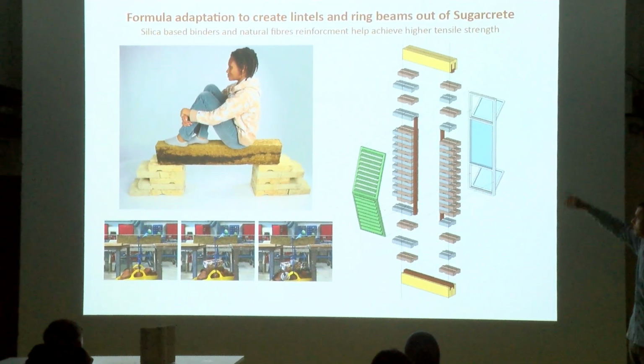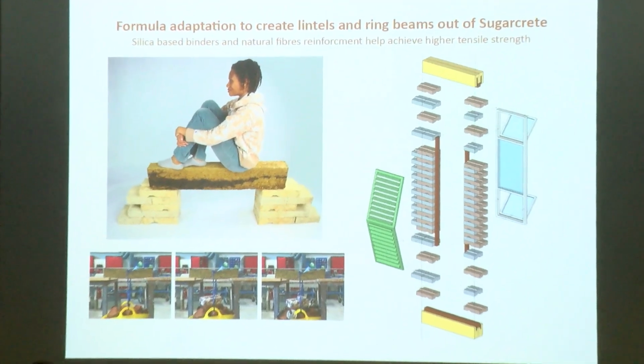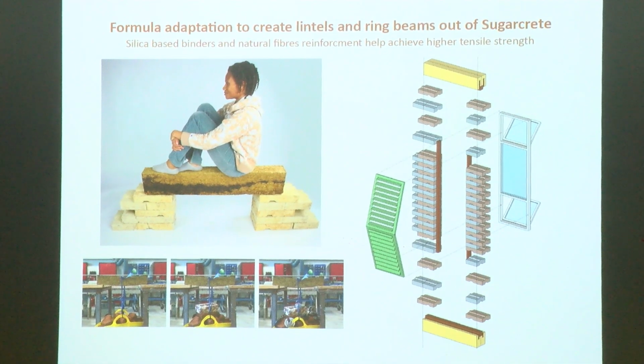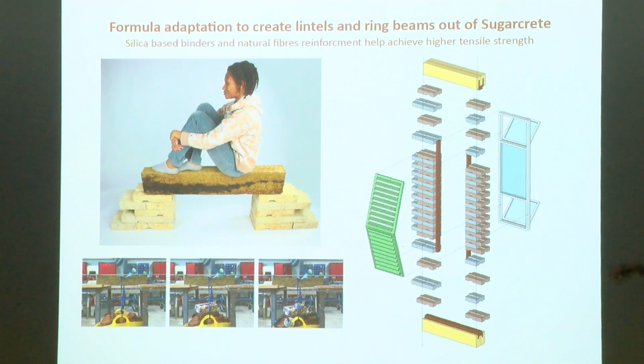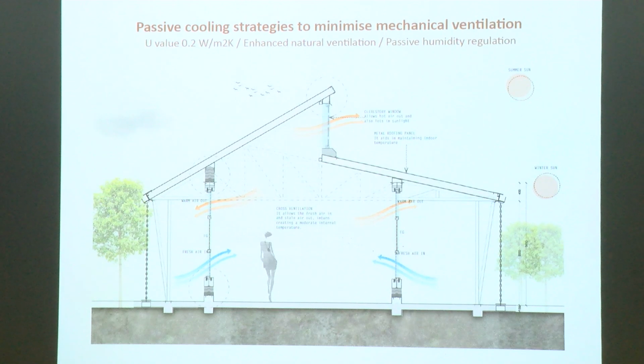And by adding that very simple mesh on the underside, it improved performance by almost 50%. This is an axo view of the window, showing how the elements come together: a timber window, operable up and down, with lintels located on the top and bottom of the windows. The top lintels are all connected, creating a ring beam or a belt on top of the wall for additional stability.